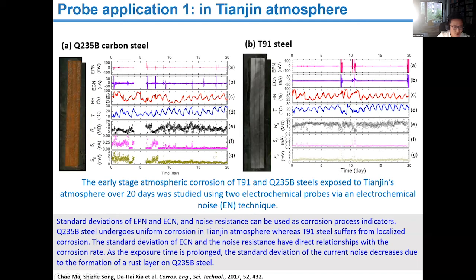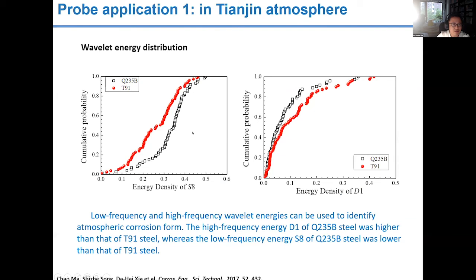Okay, so we can use wavelet energy distribution to identify the corrosion form. For the corrosion form of these two steels, the high frequency energy of Q235B steel is higher than that of T91 steel, whereas the low frequency energy S8 of Q235B steel was lower than that of the T91 steel.